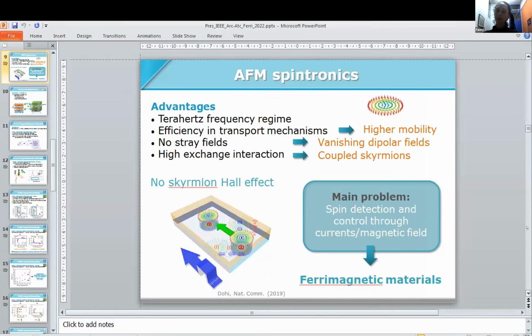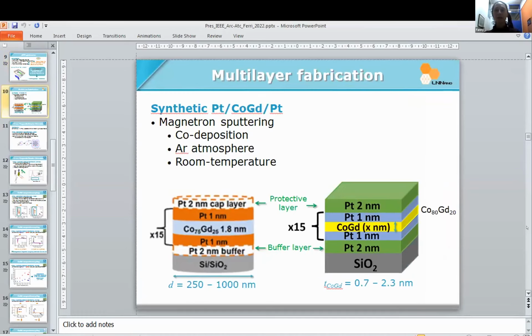So here we pass to two systems of multilayers. Both of them are synthetic cobalt gadolinium based systems. Cobalt gadolinium will be the ferrimagnetic part, with platinum at the top and at the bottom. Both were deposited by magnetron sputtering, by co-deposition at room temperature.